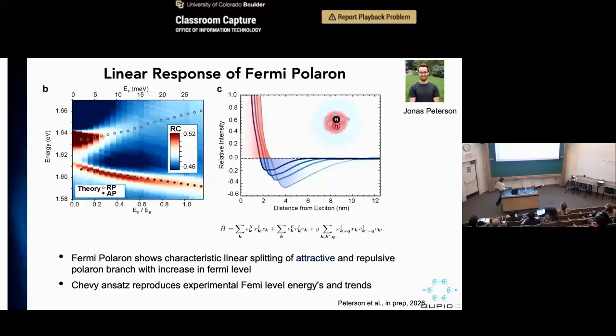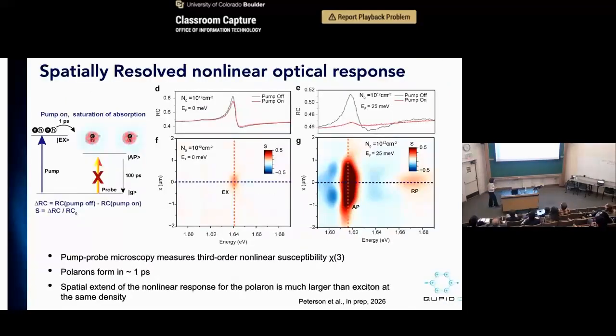I know I don't have a lot of time, so I'm going to cut to the chase. If you can indeed reach a much larger interaction length scale, one of the signatures you can look at is how nonlinear the exciton becomes with charges. Nonlinearity can be measured in the pump-probe measurement I just mentioned. In this case, what you want to look at is the linear absorption, which is the pump-off black line, and how much that can be modified under a pump-on condition, where you are already generating multiple excitations, and you look at the linear absorption with the other excitations around. If you have very strong nonlinearity, then you can totally saturate out this transition.